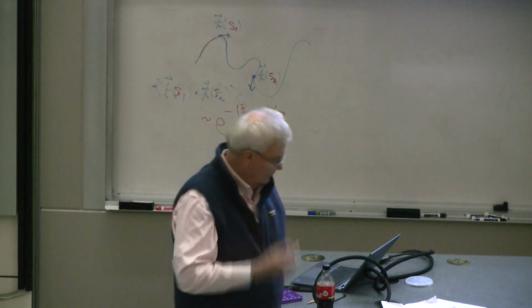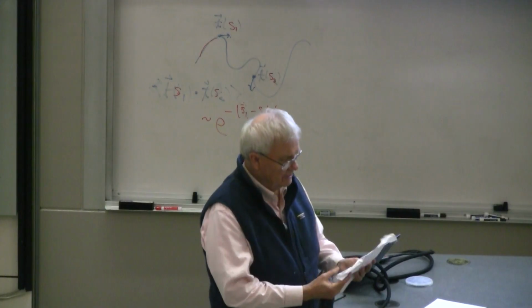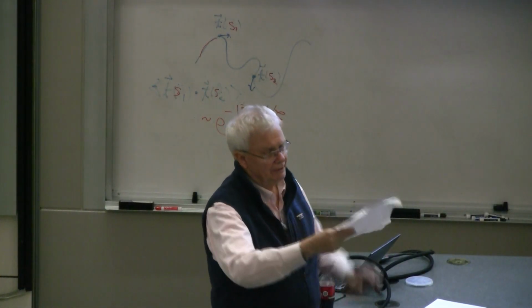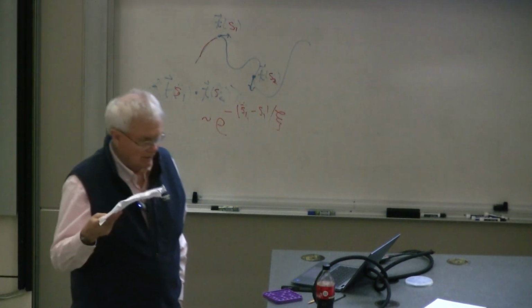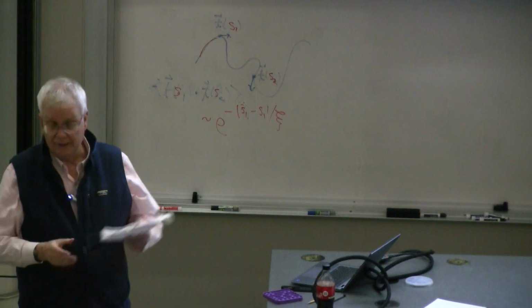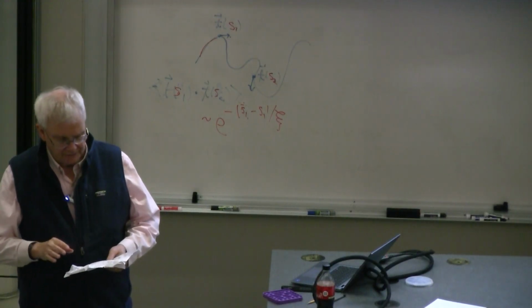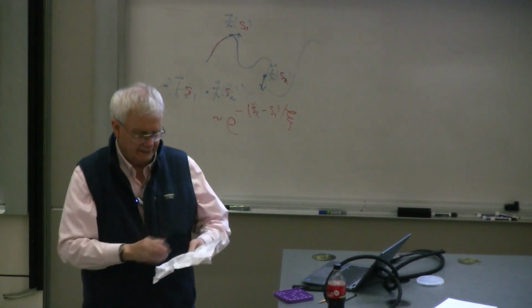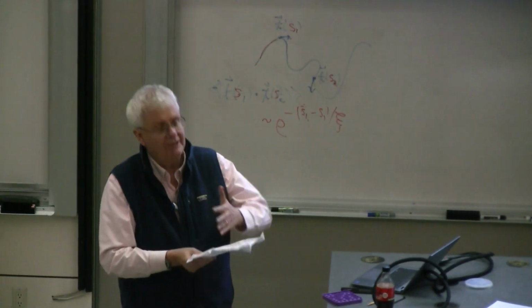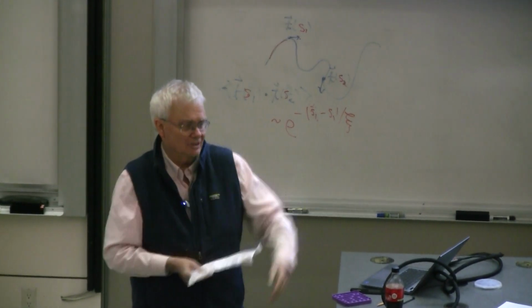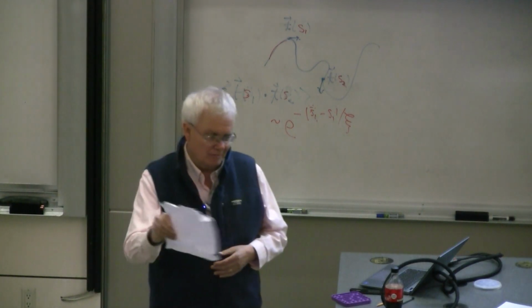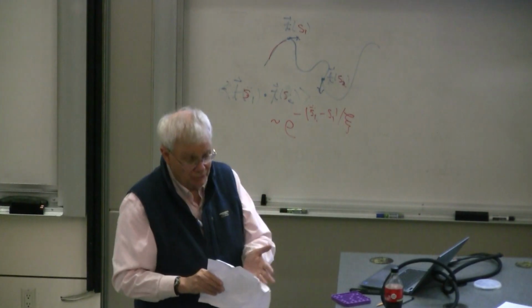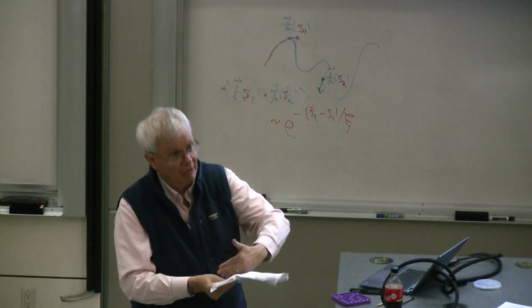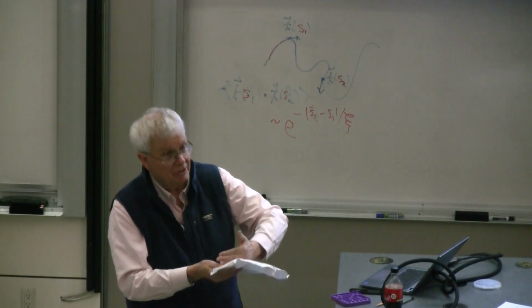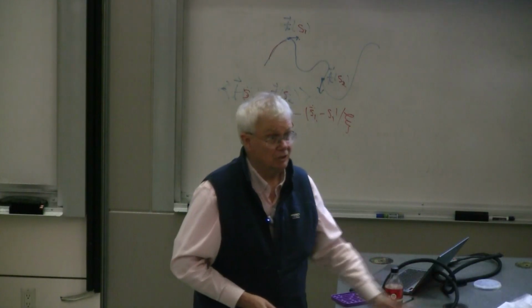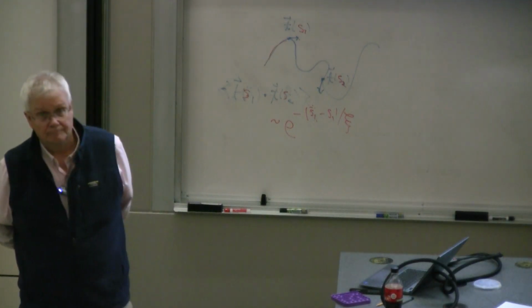My colleagues at Argonne and Penn State imagined that, okay, they get a 25-fold enhancement by putting in their ripples, by templating aluminum oxide off the rough side of one of these silicon wafers, and they imagined cutting it and tailoring it down and sculpting out a material that has an intermediate bending rigidity. And so, it depends on what the application is. If you want to have something that's going to be a sensor that has a certain resonant frequency, you want to be able to tune that. Maybe this is too big, then you cut it a little bit and get somewhere in between the 25-fold enhancement and the bare bending rigidity that you might have gotten or expected from density functional theory and so forth.